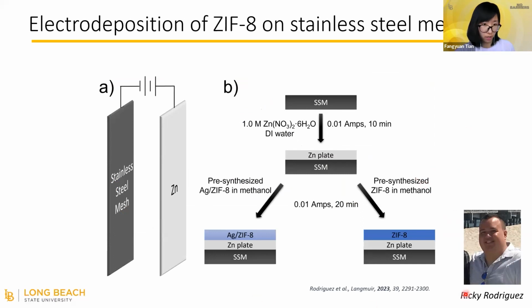So my graduate student, Ricky Rodriguez, started with an electrodeposition process of building ZIF-8 on a stainless steel mesh. He started with directly building the ZIF-8 on top of the stainless steel mesh, but it didn't work. So he found out we need two steps. The first step is to attach a zinc plating on top of the stainless steel mesh, and then he could incorporate the ZIF-8 directly on top of the zinc.